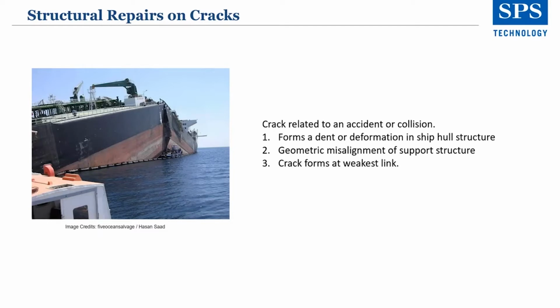Almost 40 to 60% of the accidents involving cargo ships are due to collision or grounding accidents. Human errors in operating and manning these ships is one of the primary reasons for the accidents. This exceeds other causes such as technical or mechanical failures, design issues, and environmental conditions. The shipping industry has to be cautious towards accidents, as there's no such thing as an insignificant leak that is acceptable anymore. In an extreme event, such as a collision or a grounding accident, as a result of human errors or not, a high level of redundancy will be crucial in limiting the extent of the damages to the ship's hull and the potential for further unexpected consequences.